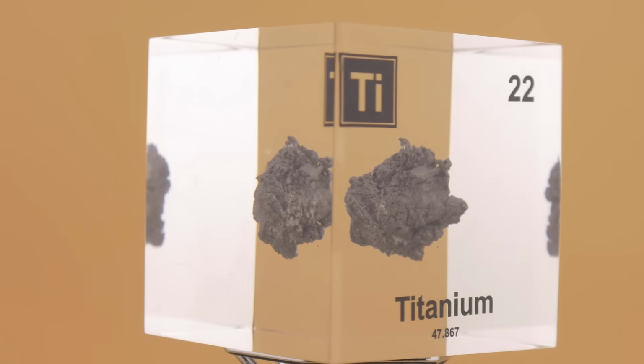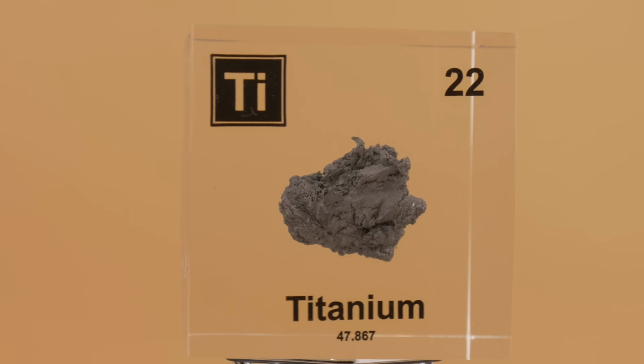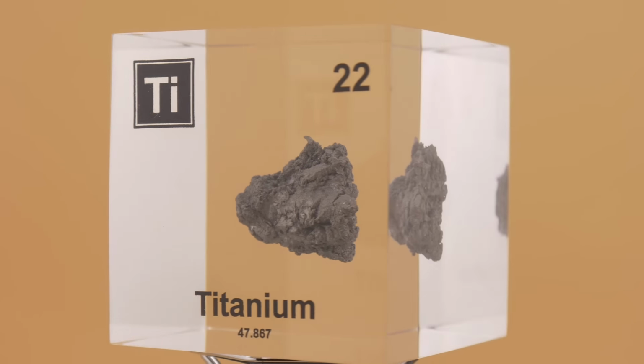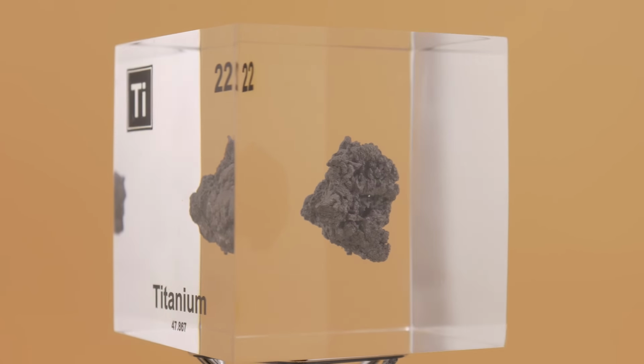Now, because titanium wants oxygen and other non-metals so badly at high temperatures, we melt or cast titanium in vacuum or inert gas only. If you try to melt titanium in an open-air furnace, you'd end up with a fire and a mess of brittle compounds, not useful metal.